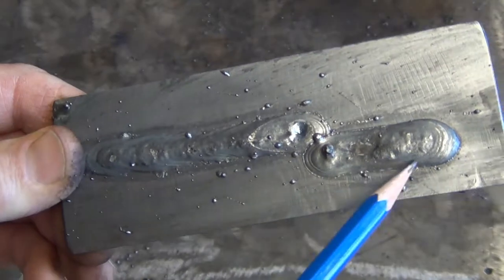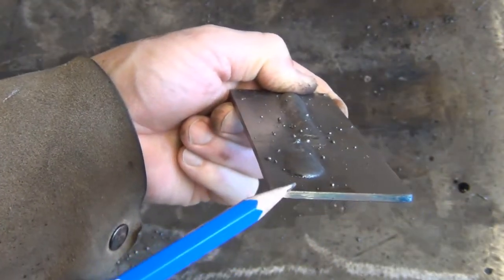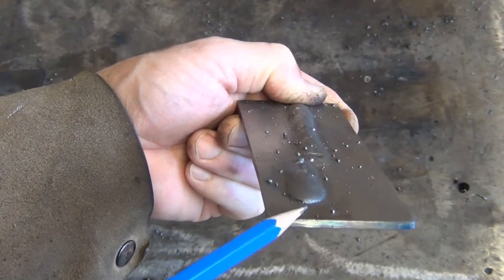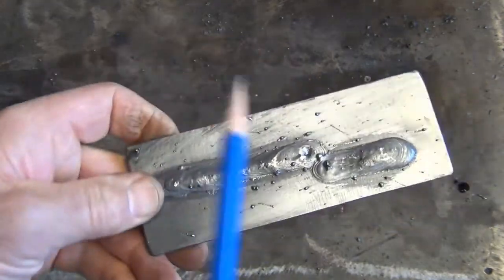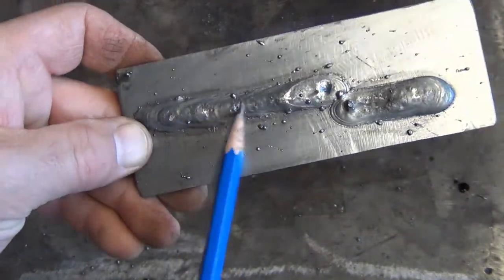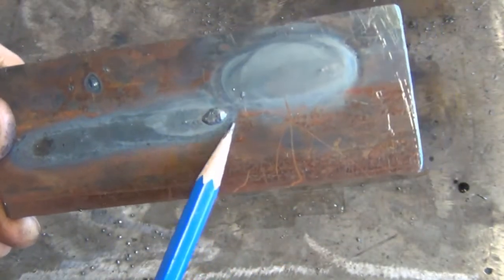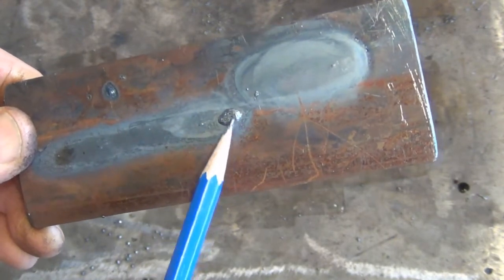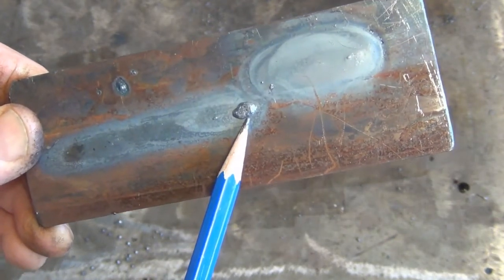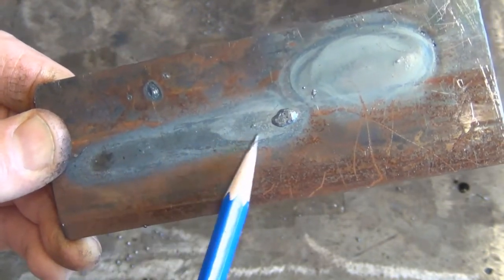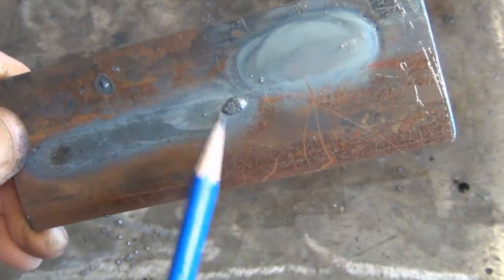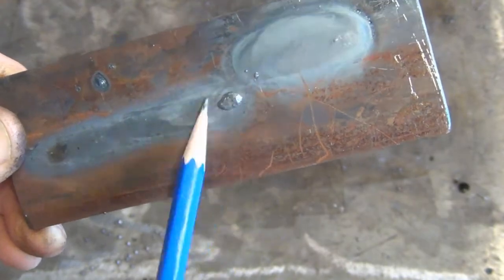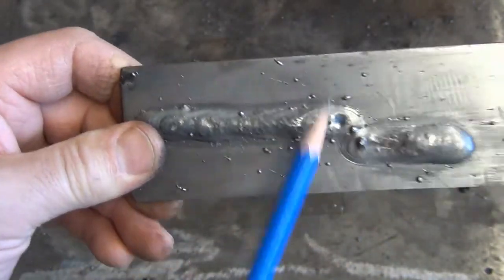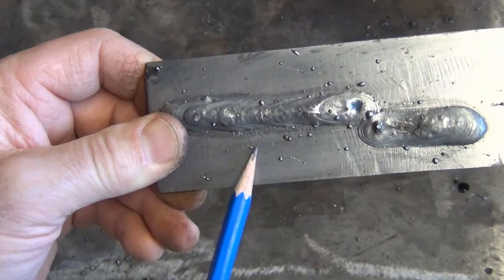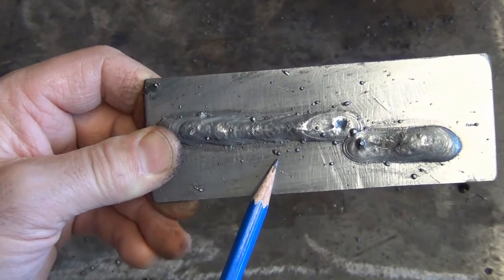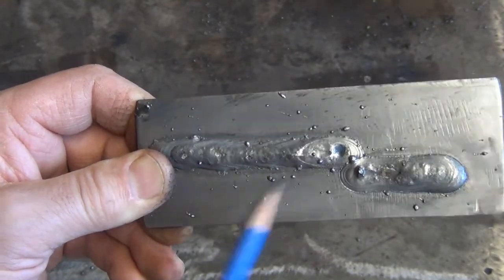This one, way too much heat. Look at how wide that profile of that weld is. It's darn near flat in relation to the height of the weld. This was very hot. And as a matter of fact, on the bottom, we can see where it's actually cratered right through the host, which we don't want to have. A little tiny pimple every now and again, that's the absolute max, but this is quite significant. Way too much heat. So on this one, I look at that and I know I'm way too hot and it's quite excessive. I'm going to slow it down, maybe 2 adjustments, and take another pass.